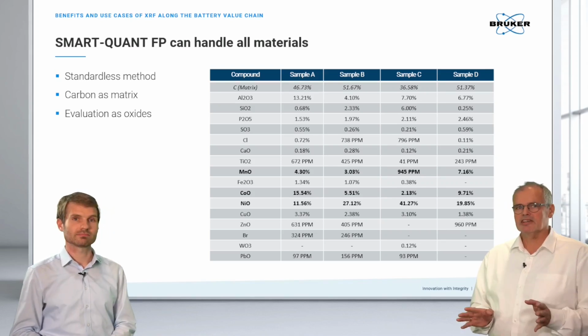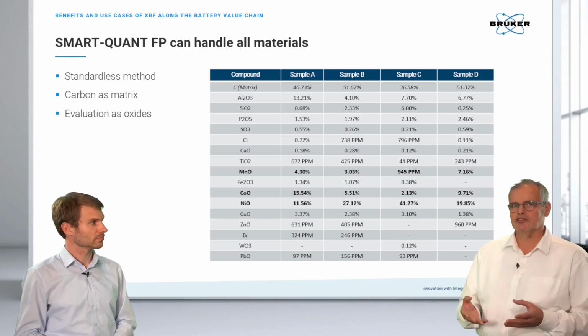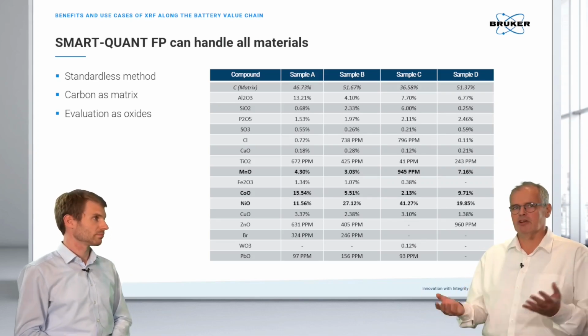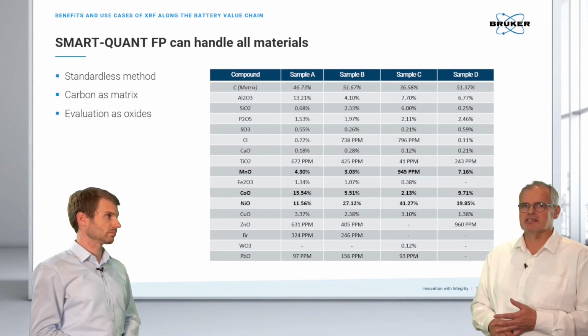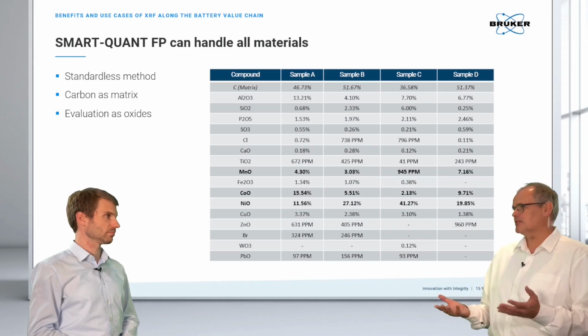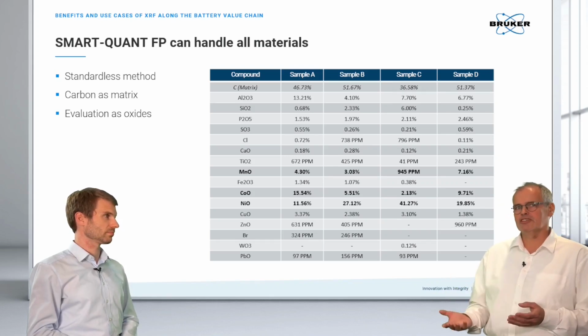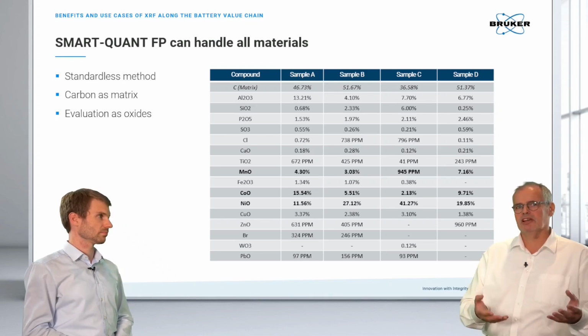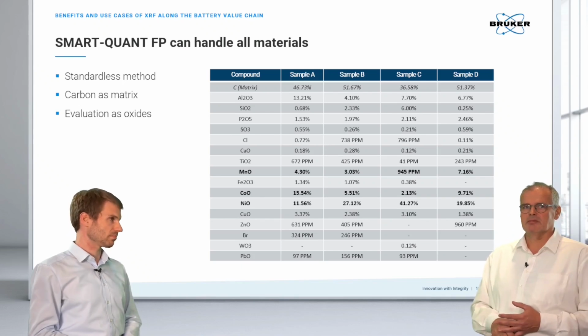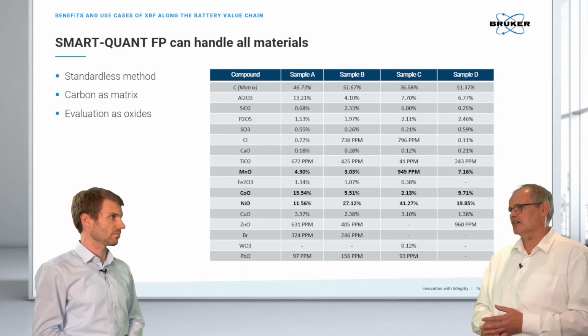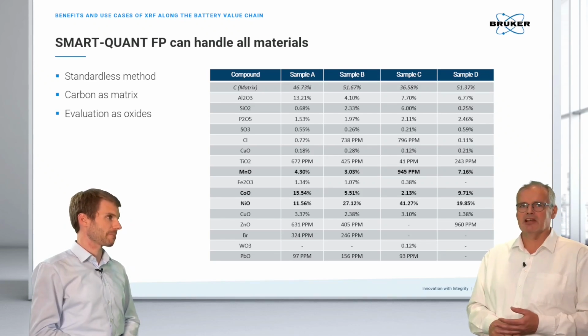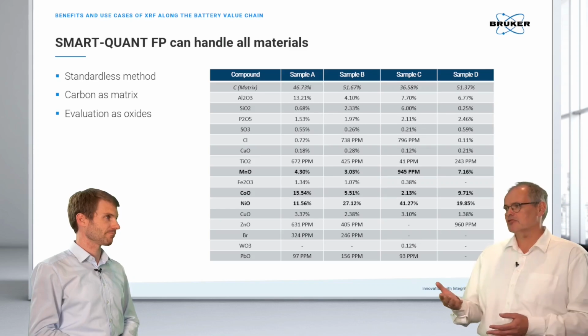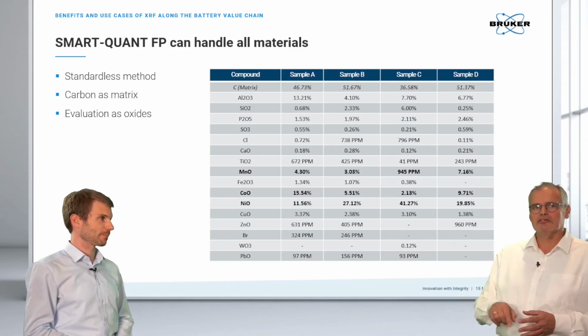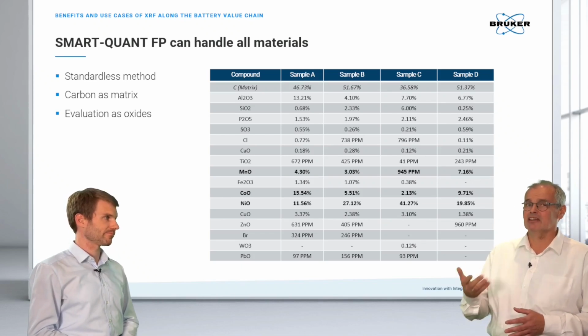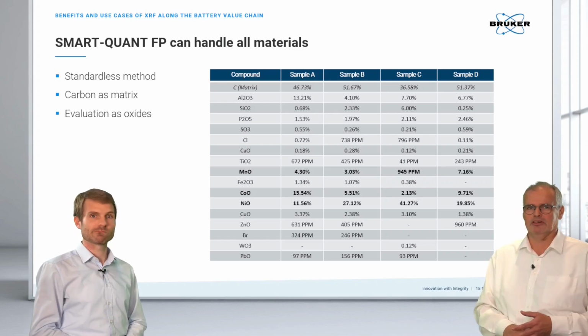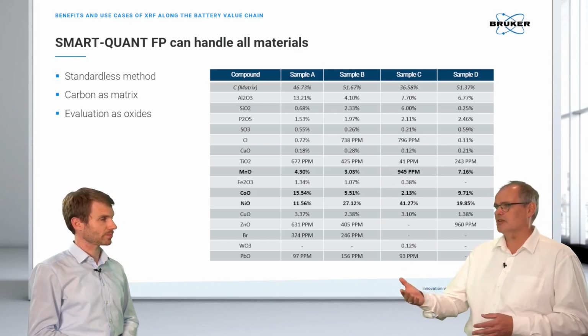The good thing is that typically in a calibration you have elements of interest. So you would calibrate, in this example, maybe nickel, manganese, and cobalt. Nevertheless, in a recycling process, there's always a risk of contamination. Some foreign material will go inside, some other metal parts which are shredded and suddenly show up in your black mass fraction, and suddenly you see some elements which you don't expect, like titanium. The good thing using SmartQuant FP is that the titanium will be evaluated and show up as a data point. So you would see, hey, I have a contamination in my material.